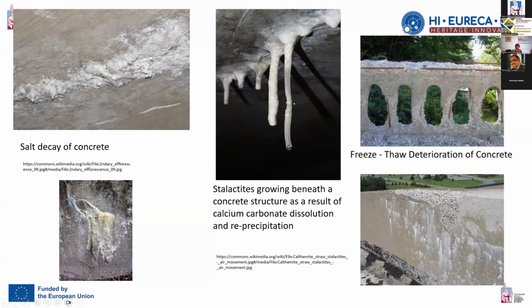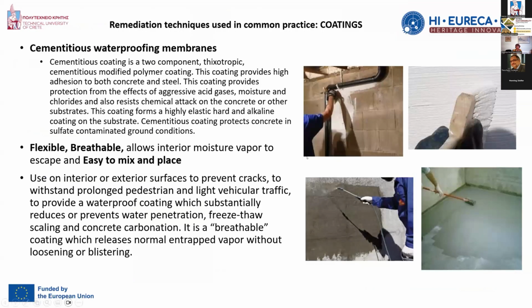In this image, you may see the stalactites growing beneath a concrete structure as a result of the calcium carbonate dissolution and reprecipitation, another decay factor of concrete. And of course, there are severe decay when the concrete structure are undergoing this freeze-thaw deterioration of concrete.